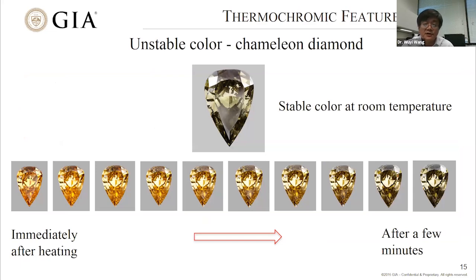Another example is a very well-known chameleon diamond. The color is not stable; it changes. What I show here at the top is a chameleon diamond. A stable color shows a yellowish, brownish, green body color. This is a stable color at room temperature. When this diamond is heated by an alcohol lamp, for example, to a few hundred degrees C, it turns to a beautiful, vivid, very bright yellow-orange color.